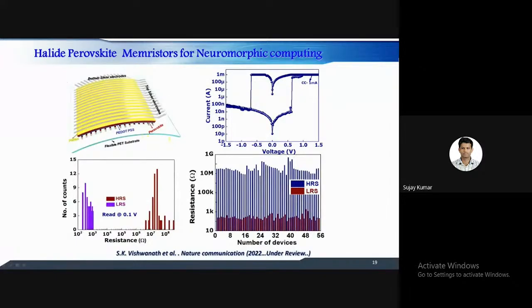What we observe is similar kind of characteristics, with a high switching on-off ratio of 10^6. We can measure almost all the devices with a particular resistive on-off ratio. We measured more than 56 devices here, and all of the devices show similar, comparable resistive switching.